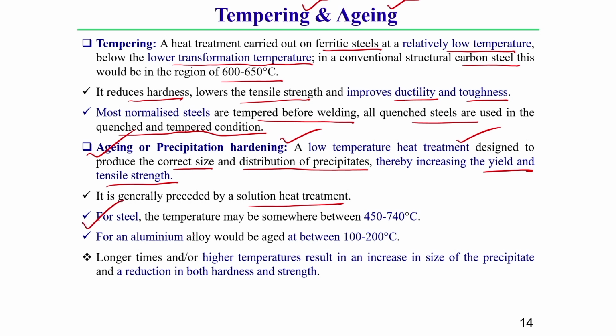For steel, this precipitation heat treatment temperature is somewhere between 450 to 740 degrees centigrade, whereas for aluminum this temperature varies within a range of 100 to 200 degrees centigrade. Here one thing you should keep in mind: the longer the time of this aging hardening, or the higher the temperature of this aging hardening, the greater the increase in size of the precipitates, and if the size of the precipitates increases, it reduces both hardness and strength. This you should keep in mind.